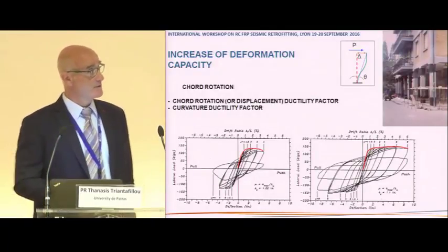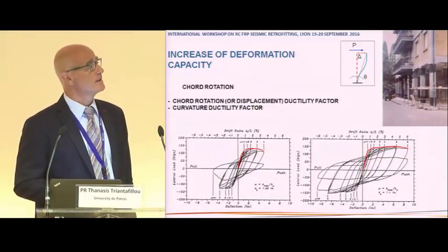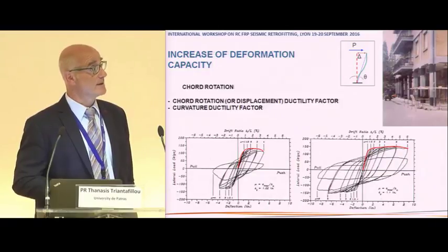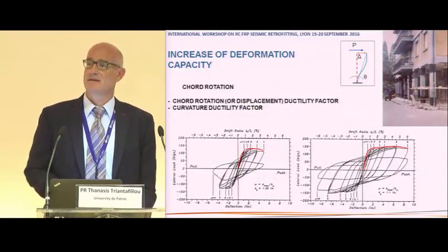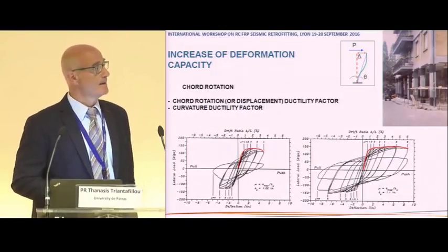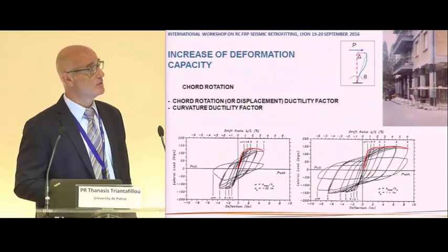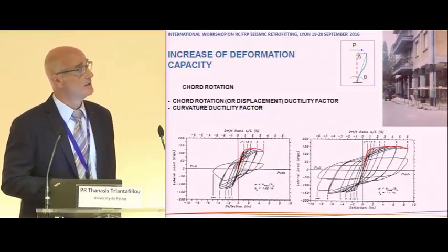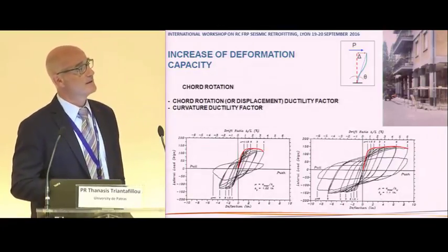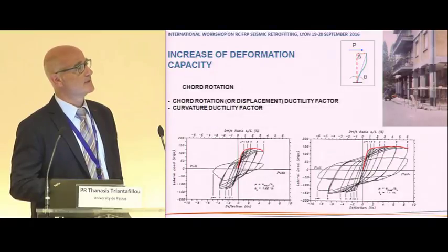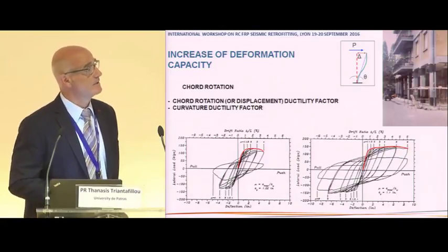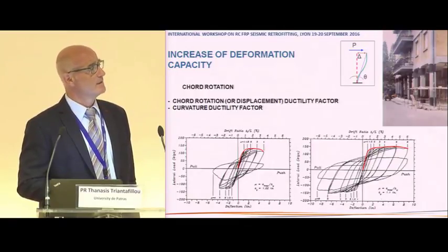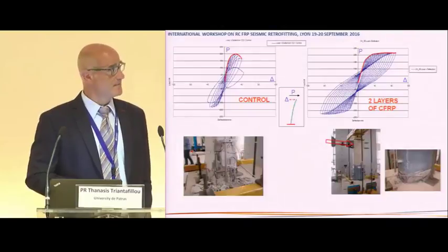Another reason, a very important reason to do confinement in columns is when the objective is to increase ductility, to increase the deformation capacity. Typically, this deformation capacity in columns is quantified by the chord rotation of the member, or by the respective ductility factor. The chord rotation is basically this angle here, the angle measured between the axis of the member prior to deformation, prior to the lateral displacement, and the chord of the member at failure, the ultimate value of that chord. This is what I have to increase when it comes to increasing the deformation capacity.